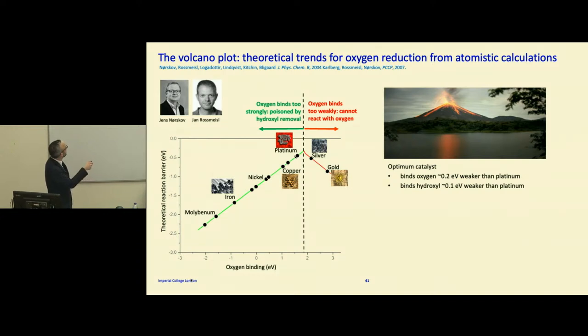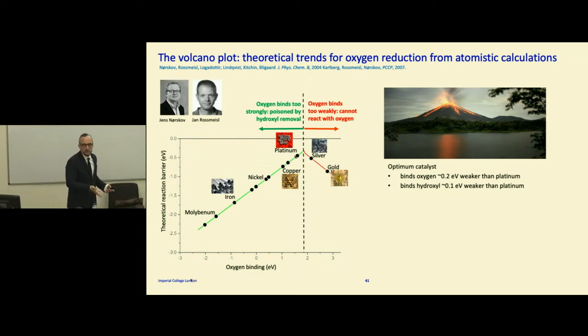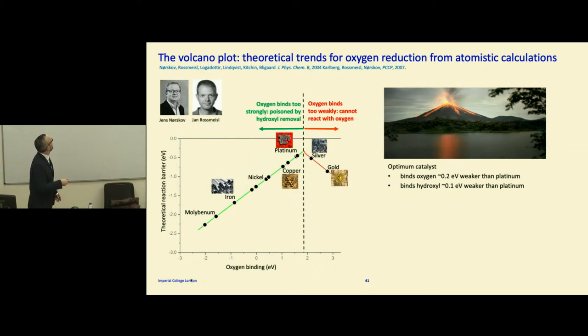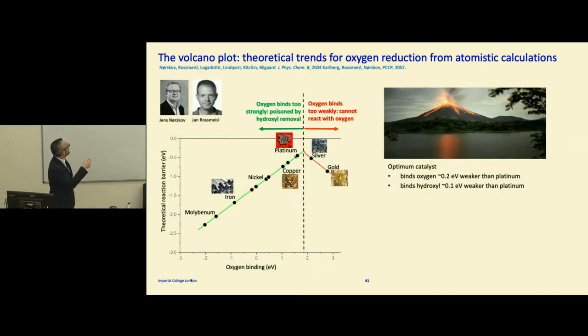Or if you look at a very reactive surface like molybdenum or iron, you know, iron reacts readily with oxygen to make rust, you'll also get poisoned by the reaction of oxygen. So platinum is actually ideal because it has a moderate binding to reaction intermediates. You could get even higher if you just weaken the binding to oxygen a little bit further. So this is what the volcano plot shows.